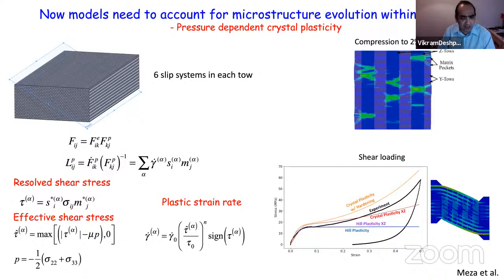And this is really important because you think this is a shear test. Why would I get pressure building up at all in these specimens? But you do get buildup of the pressure effectively because of the three-dimensional nature of that architecture and the mismatches, basically the anisotropy, between each toe. So you can see that you need the pressure dependency.